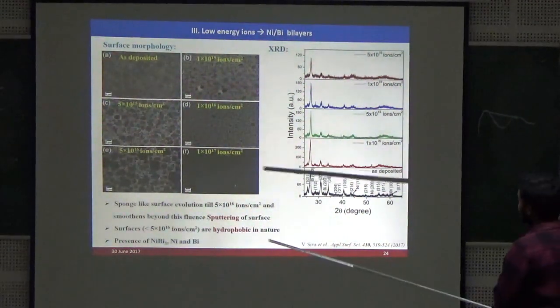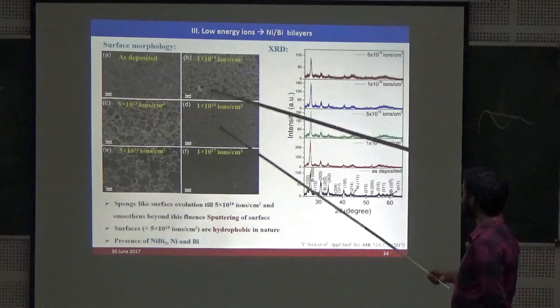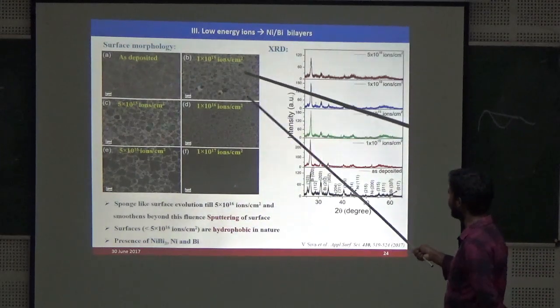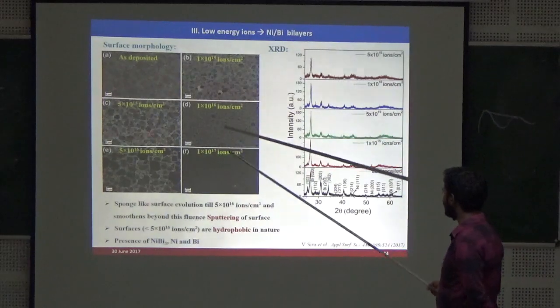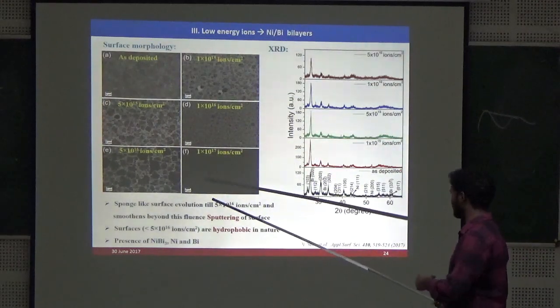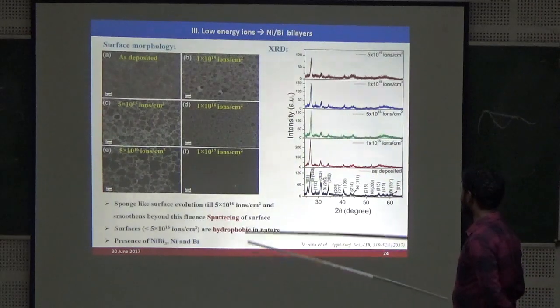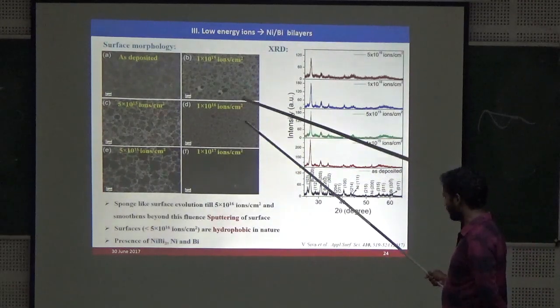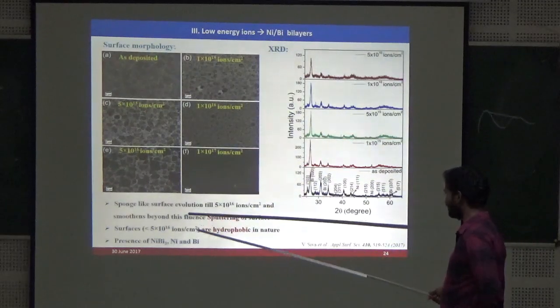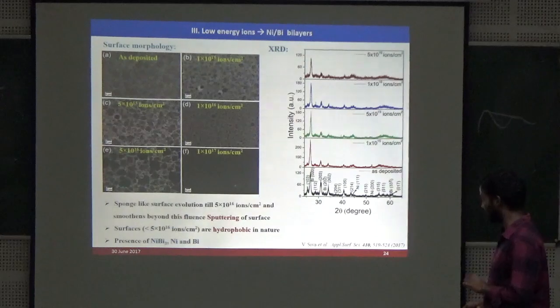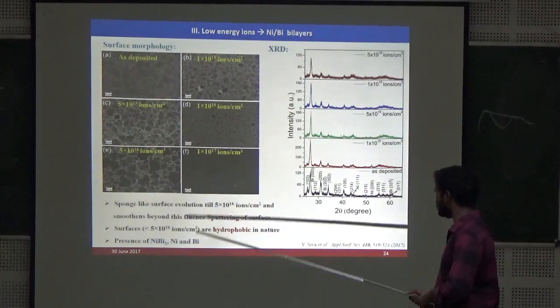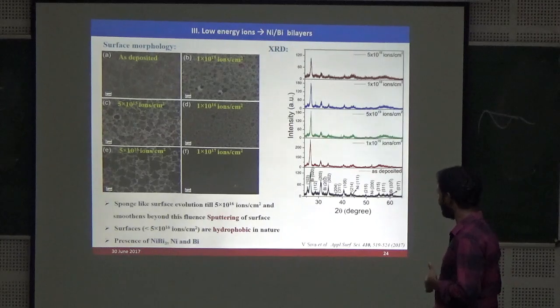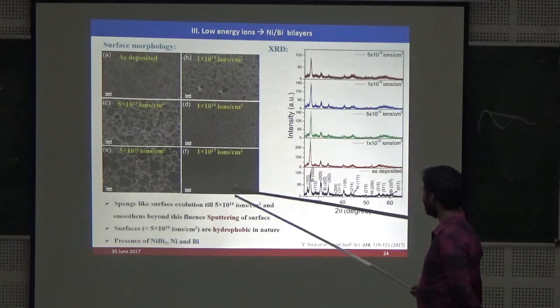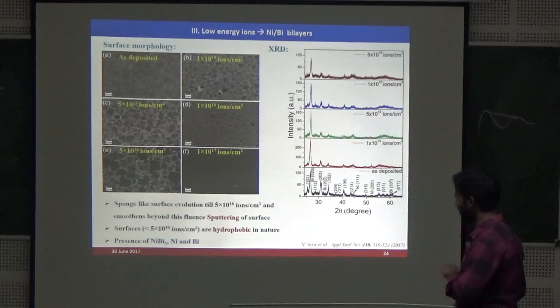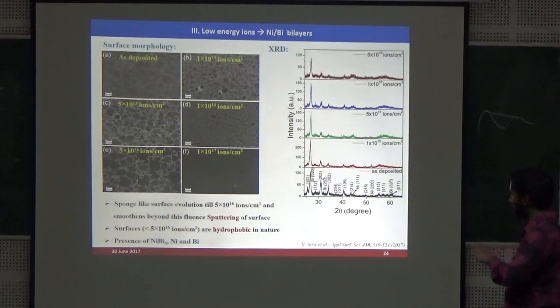In this case, we have performed the SEM measurements. So you can see at the lower fluences, after the irradiation, we have seen a small-scale surface morphology. It was due to sputtering of surface atoms, and these films are actually hydrophobic in nature. That means one can actually use this coating for anti-rust, to avoid rusting. And after this phase, it mostly smoothens the surface because of large sputtering. Most of the bismuth layer is sputtered. That I will show you in RBS measurements.